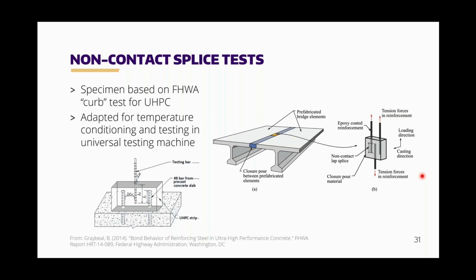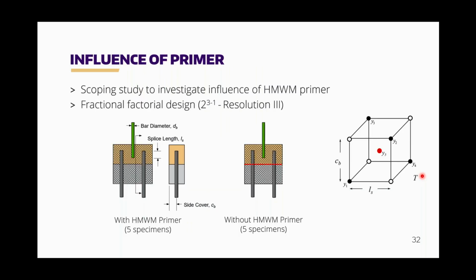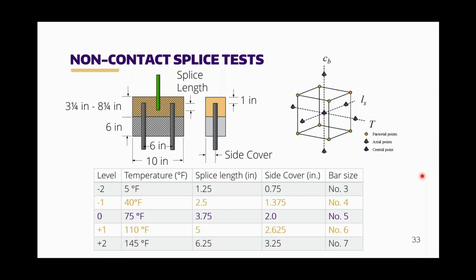So you can sort of see how this non-contact splice test would mimic that of a closure pour. That's the figure on the right-hand side. So we're providing tension between the closure pour and your prefabricated element, and that tension is being applied to the reinforcement. At the very beginning of this phase, we did a small scoping study to investigate the influence of primer. That would be primer applied to the cold joint as well as the reinforcement between a cementitious concrete and a polymer concrete. The brief summary of that is it makes a small difference, but for the rest of our research, we followed the guidelines of the material and the manufacturer, which meant that we did apply primer to all of our specimens.